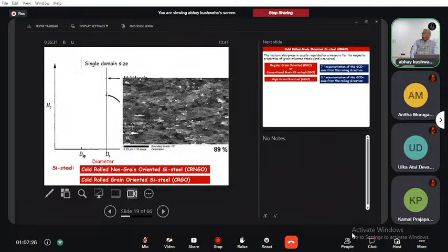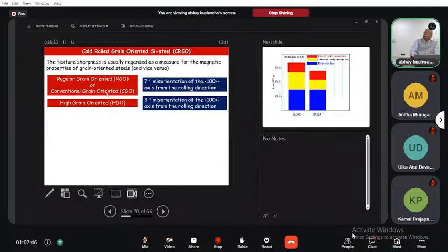Some effort is going on at Jindal Steel to prepare this CRGO. But the CRNGO is produced by many of the steel industries. Out of these, CRGO is the better variety, and again there are two types of silicon steel. One is called regular grain oriented, where the orientation of the easy axis has 7-degree misorientation, and another is high grain oriented steel, HGO, where 3-degree misorientation from the rolling direction is taking place.